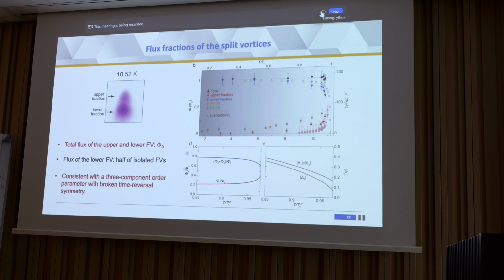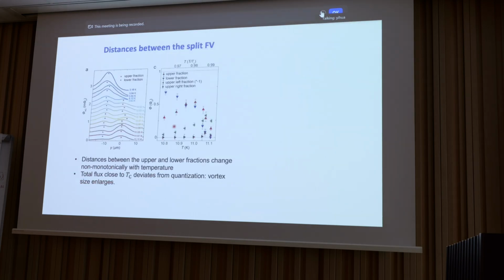And Julian has done some modeling for us using a three-component order parameter with broken time reversal symmetry. And the qualitative behavior is consistent with our measurements. However, there's a caveat, which is that their modeling actually only works around Tc. And as you can see, our measurement goes down to very low temperatures. There are also some other features from the splitting motion. One is that the distance between the upper and the lower fractions does not change monotonically. It tends to increase as the temperature increases, but then it comes back again at this temperature. This is consistent with the fluctuation very close to Tc, which has been reported earlier in these material systems.